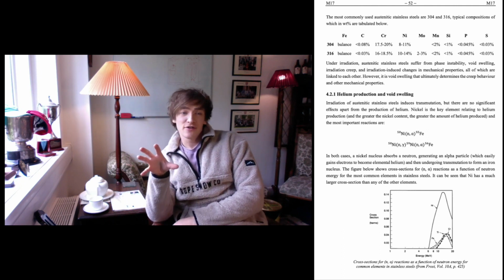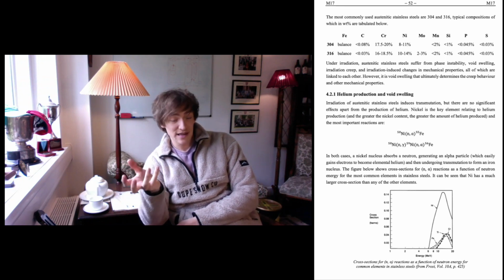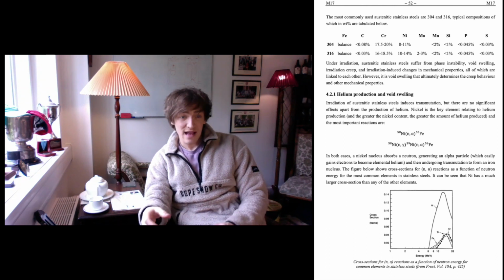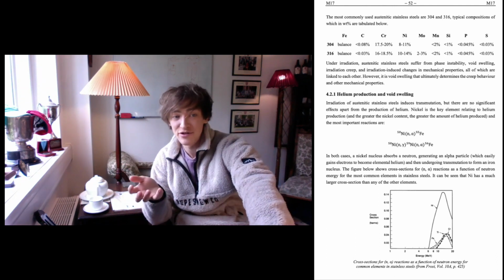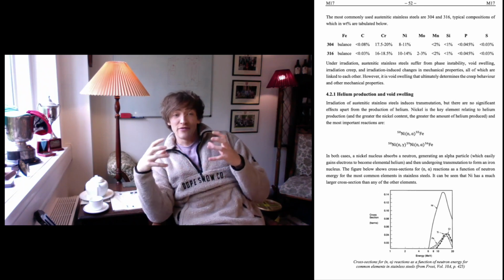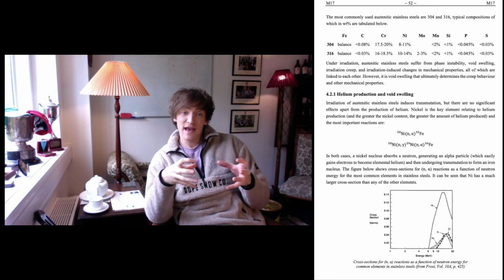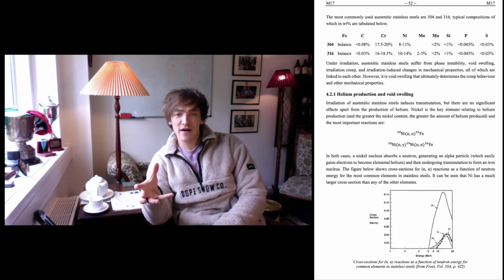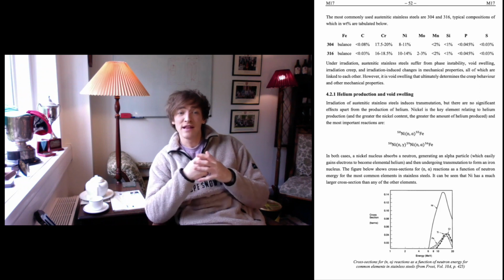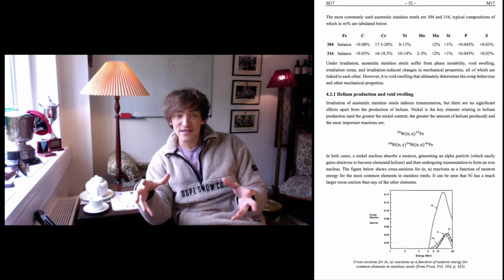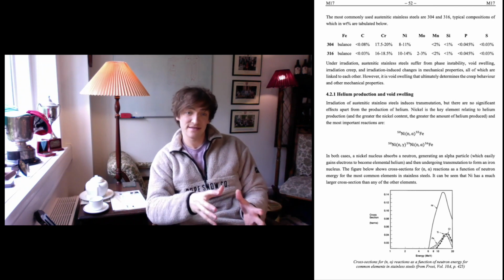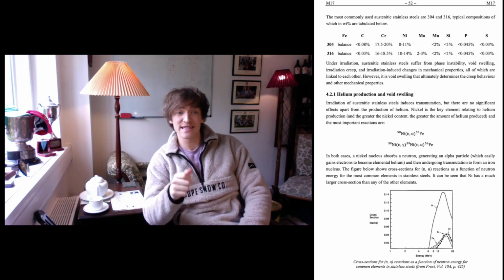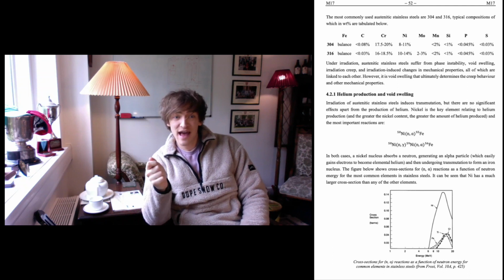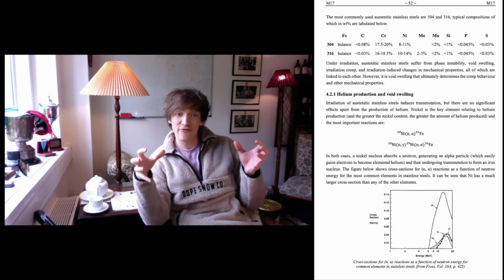Why? Well, irradiation of austenitic stainless steels induces transmutation, notably to form helium. Nickel is the key element relating to helium production, and so the greater the nickel content, the greater the amount of helium produced in your alloy. So you get a neutron, it comes through. The most important reactions are nickel-58 absorbs a neutron, becomes iron-55, because it absorbs that neutron and spits out an alpha, as shown in your notes here. And then you've got nickel-58 going to nickel-59, which then decays by alpha decay to iron-56. And the worry there, in both of those reactions, is that alpha particle that you're spitting out. The generation of that alpha is what we're worried about here, because the particle will gather electrons and become